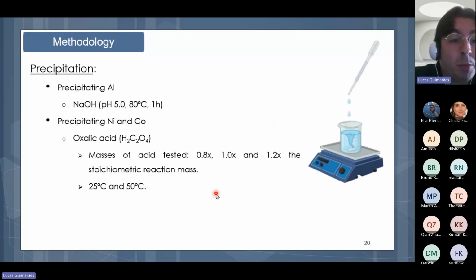Then we studied more precipitation with different precipitating agents. To precipitate aluminum under these conditions, we used sodium hydroxide. And to study the precipitation of nickel and cobalt, we used oxalic acid as a precipitating agent. This was the methodology. Three different masses of acid were tested: 0.8, 1, and 1.2 times the stoichiometric reaction mass of this acid. And two different temperatures were studied, 25 degrees Celsius and 50 degrees Celsius.